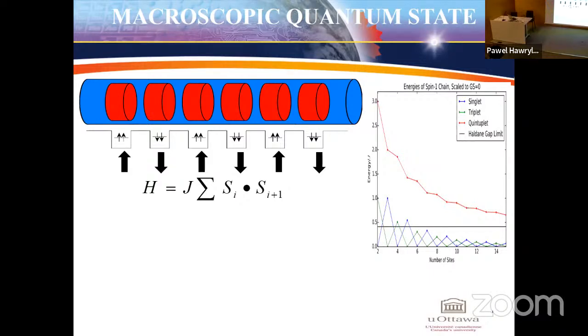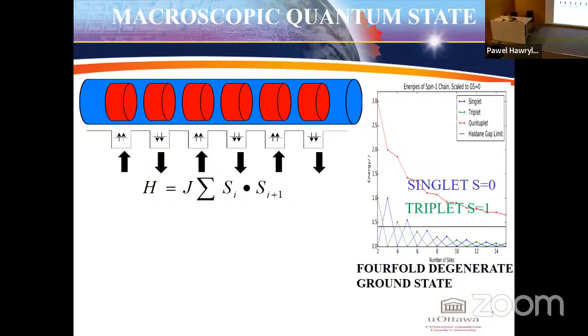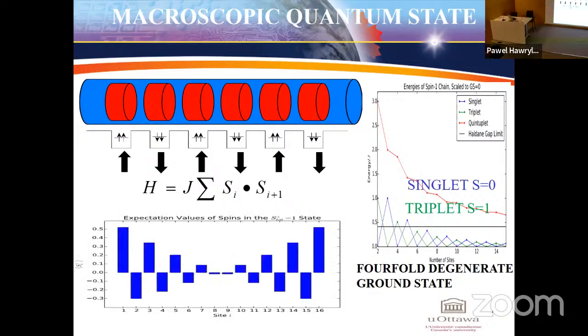And so the ground state is in the thermodynamic limit 4-fold degenerate, and separated from these hundreds of millions of states by what is known as a Haldane gap, a gap from the ground state to the triplet. This gap is about 0.4 of this exchange coupling which we computed. Yes, so we have triplets, singlets, and a 4-fold degenerate ground state, so you can do something with it. How do we understand this 4-fold degenerate ground state?